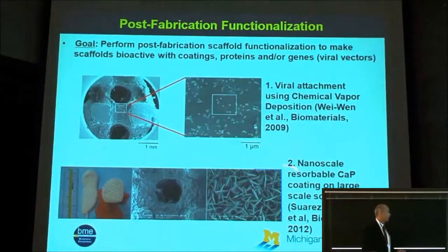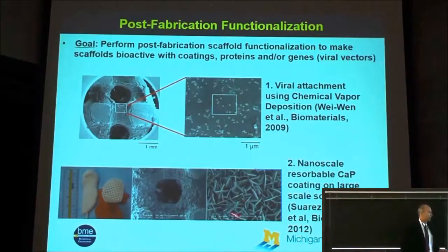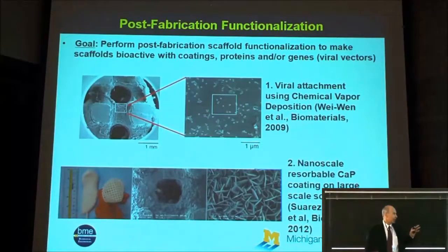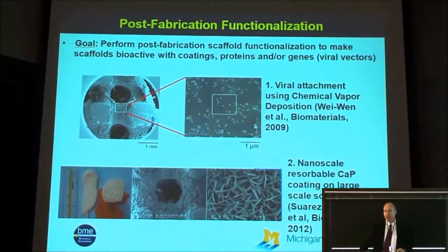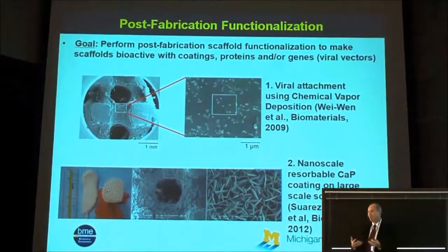So this just shows some things we've done. This is work actually with Bill Murphy. We can take these PCL constructs, and his laboratory does a technique, actually it's part of a company now, where you can coat these with nanoscale calcium phosphate coatings, which makes these constructs very good for bone regeneration. It makes the constructs what we would call osteoconductive, but these coatings are also good for delivering growth factors. The other thing is you can do this with gene therapy. We've done work where we can take viral vectors and through different chemical conjugation techniques directly attach these vectors, as you can see here, to these designed scaffold surfaces. And you can do this with proteins as well. So now you can functionalize these materials with different biologics.